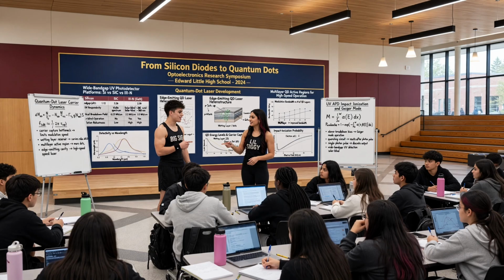Wow, they just shatter the lattice. They create what we call dangling bonds and trap states right at the interface. Over time, as you expose the sensor to UV, you are dynamically creating more and more of those stepping stones we talked about earlier. Which means the dark count rate skyrockets and the sensor just drowns in its own noise. Exactly. If you look at reliability studies on commercial silicon UV APDs, their efficiency and noise performance plummet rapidly after prolonged UV exposure. They get sunburned. We clearly need a completely different material.